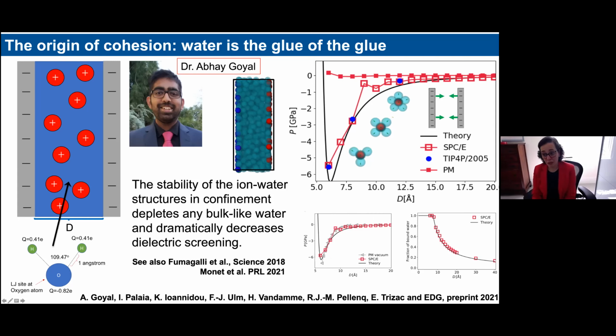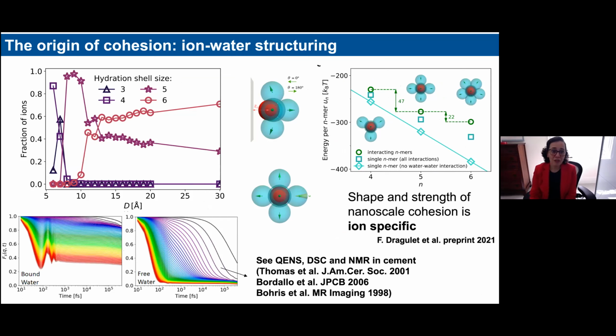We can also use the theory to predict the fraction of bound water present in the system at different degrees of confinement, and then compare it with the data in the simulation, and they agree quite well. So how does it work? Well, at a high surface charge, the ions are squeezed close to the surfaces, and they form hemispherical hydration shells with the water.